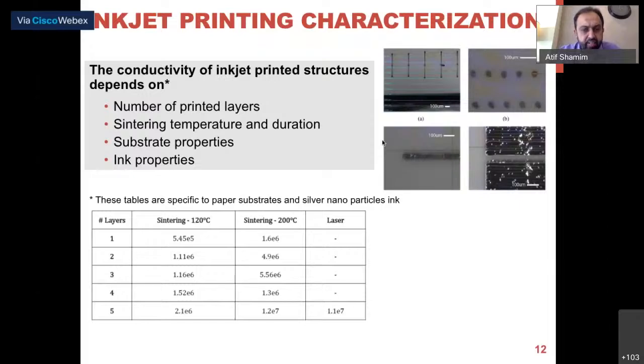And this conductivity can actually go up to 10^7 Siemens per meter, which is very close to the bulk conductivity of the metals which we typically use, like silver, copper, and gold, which are around 5 × 10^7 Siemens per meter. So we are almost close to that. Of course, this is a combination of the more layers you print and the more sintering you do, you get this kind of behavior.